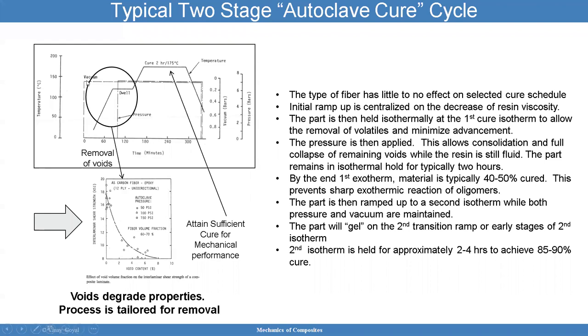The initial ramp here is centered on the decrease of resin viscosity. And then the part is held isothermally at the first cure isotherm to allow the removal of volatiles. I discussed this already. Then the pressure is applied about there. This allows consolidation and full collapse of remaining voids.